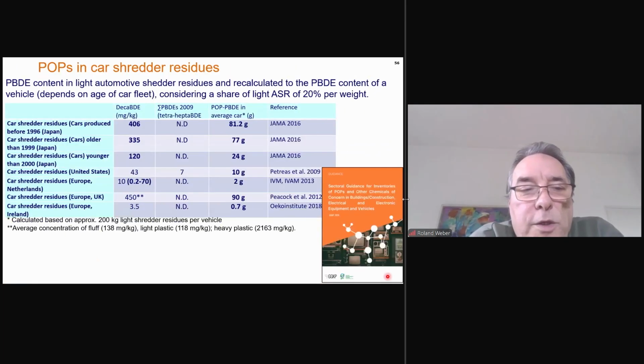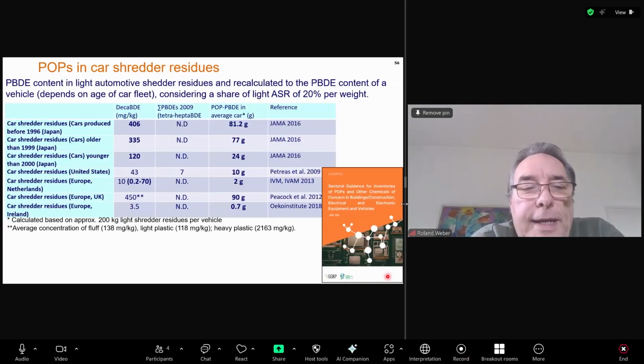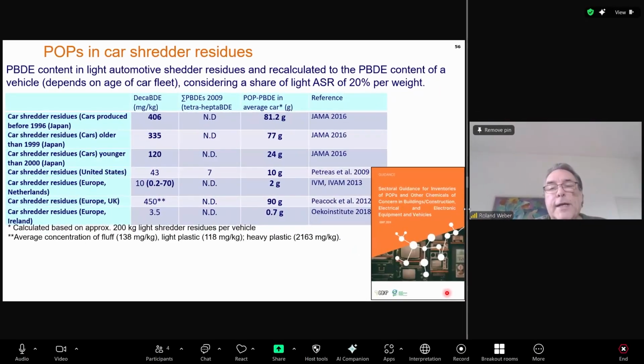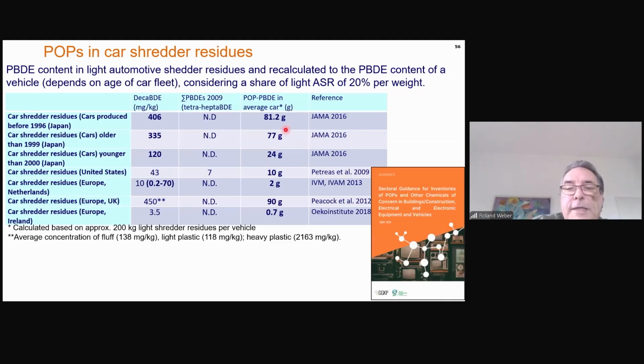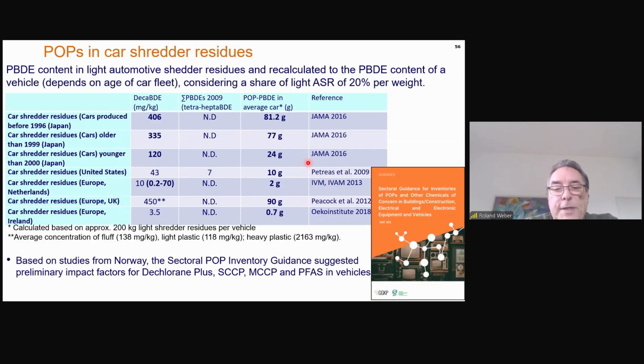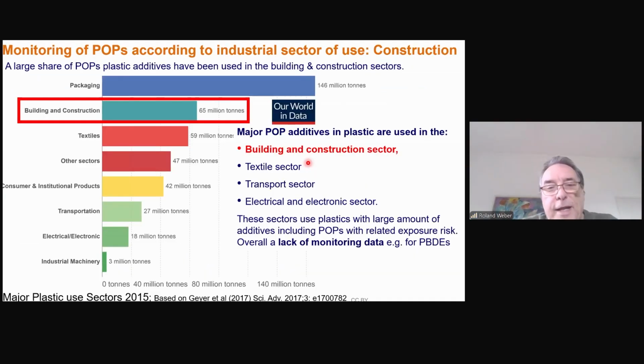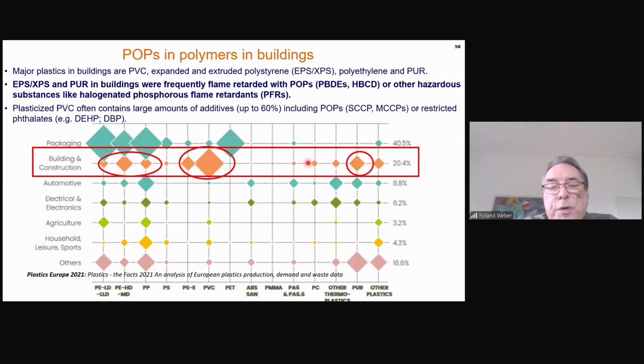And I give you here some examples. Also here, good studies from Japan. For example, they shredded cars which are older than 1996 or 1999. And you see also, like for electronics, the levels in these cars are relatively high, around 80 gram PBDEs per car. But for the cars which were younger than 2000, so they did a specific shredding for cars which were produced after 2000, only 20 gram of PBDEs were included on average. But you see the whole thing is quite complex, and I will tell you more on the complexity of end-of-life monitoring of POPs.